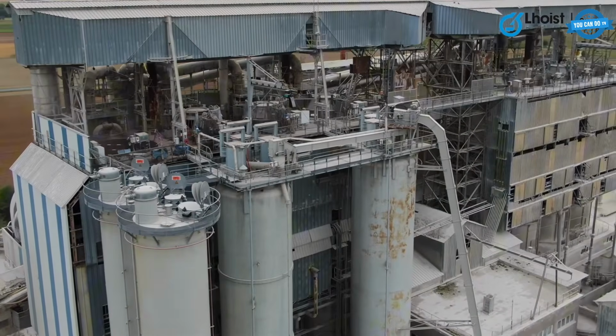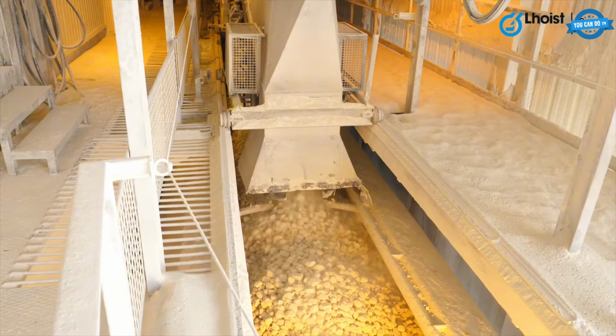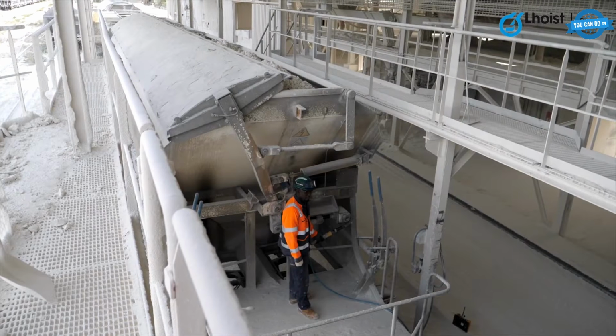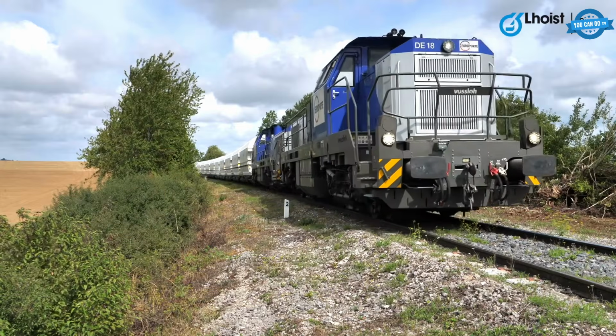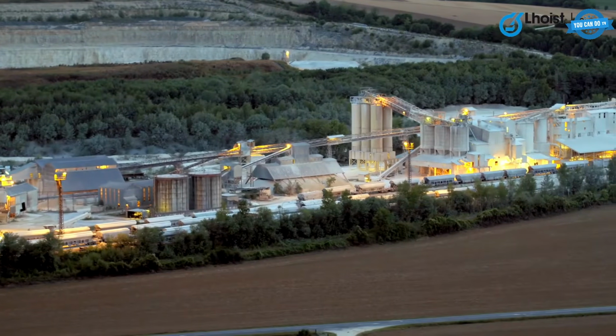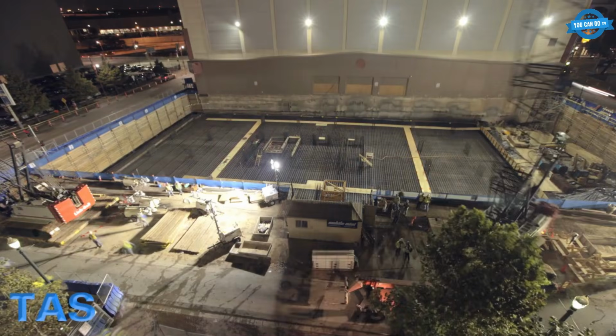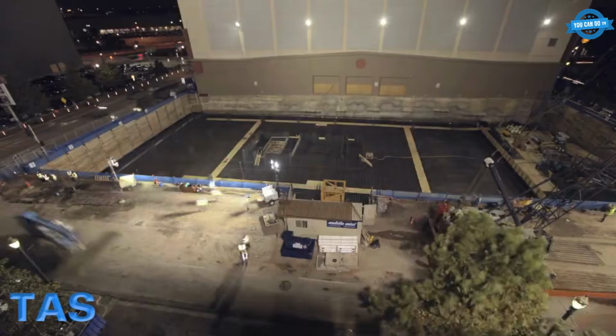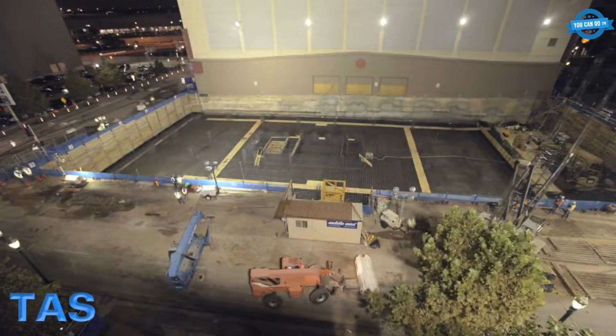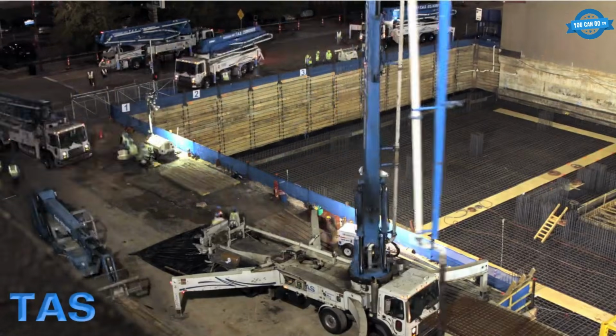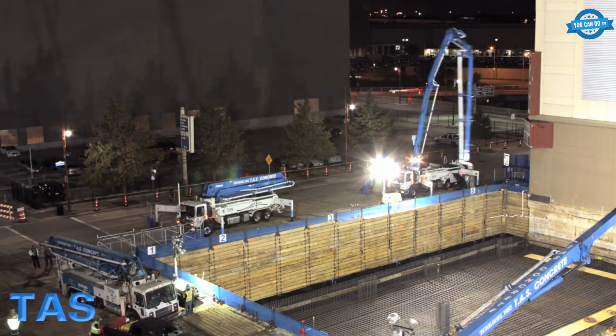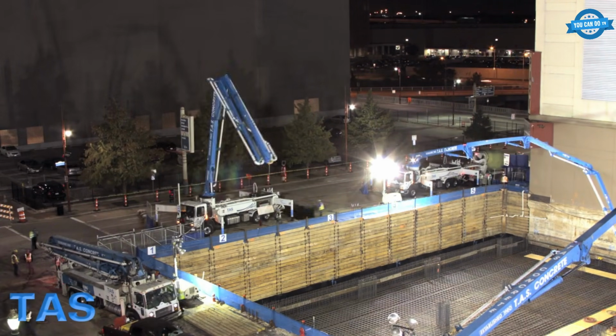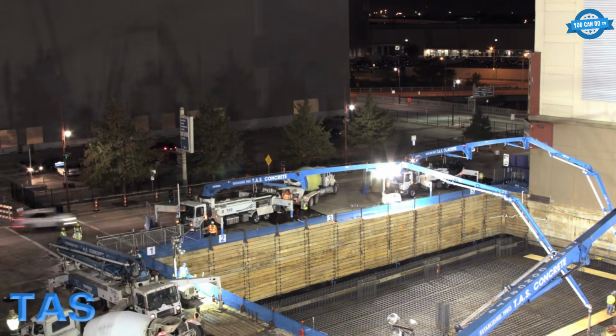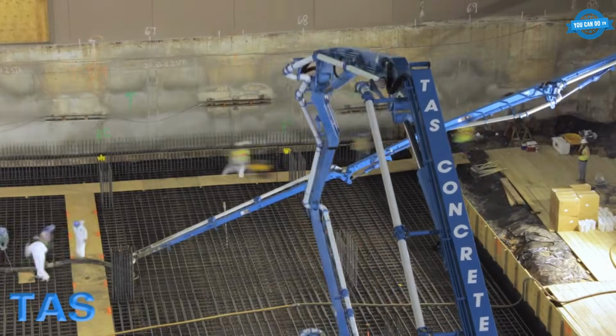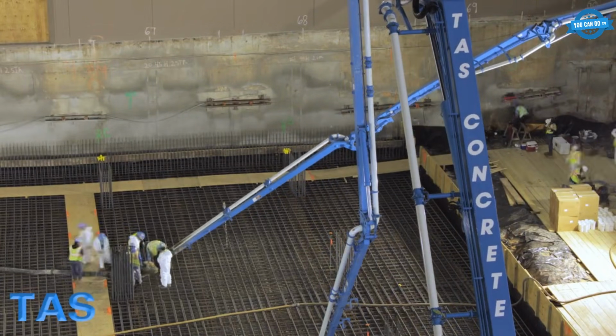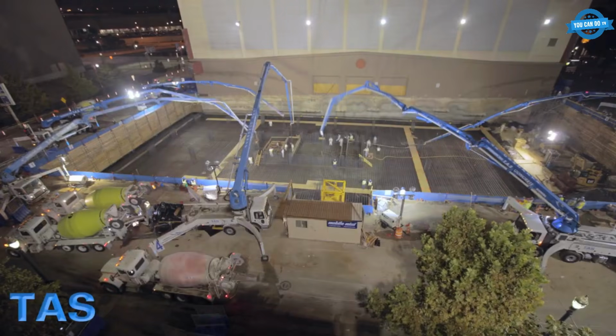And then a curious thing happens on a construction site. The powder from that kiln meets the crushed stone from the quarry, and they turn into something neither one can be alone. For the mat pour under a 40-story tower in downtown Houston, crews place 25,000 square feet of concrete in one continuous operation. 4 batch plants, 6 pump trucks, 136 mixer trucks, and 2 shifts of finishers ran for 13 hours and 16 minutes without stopping.